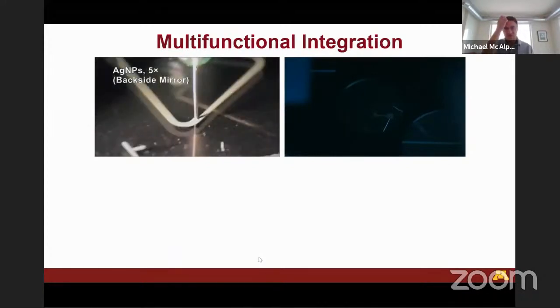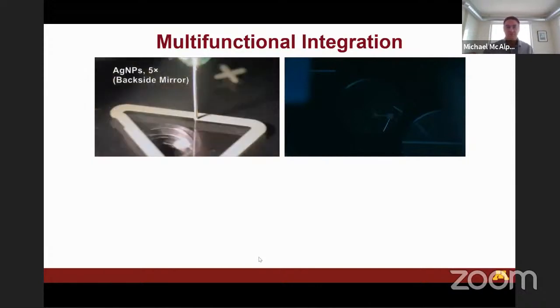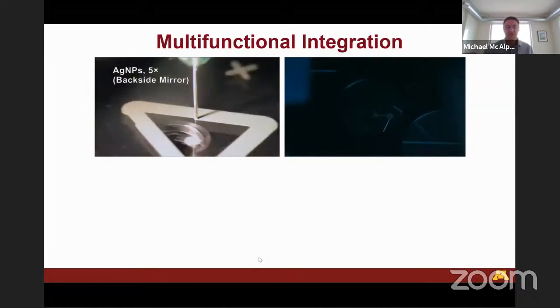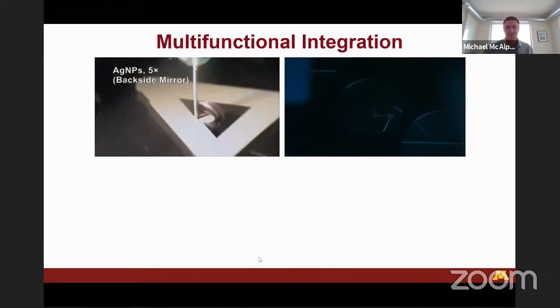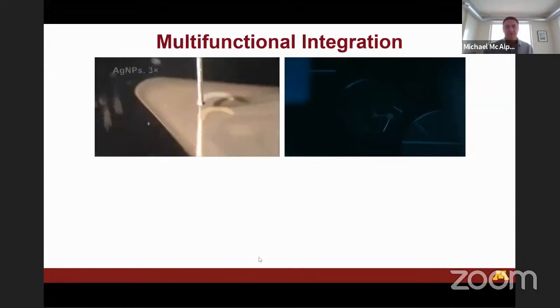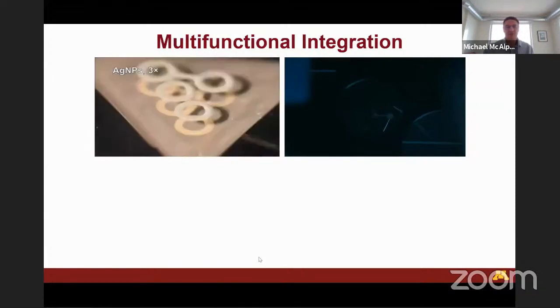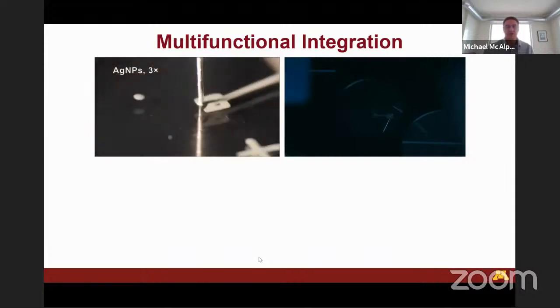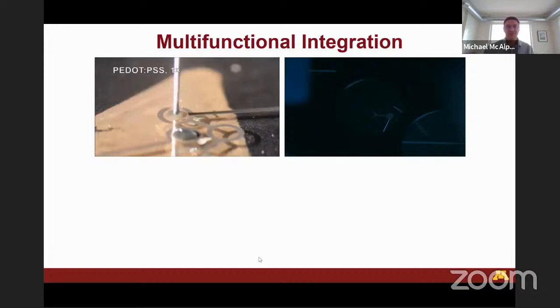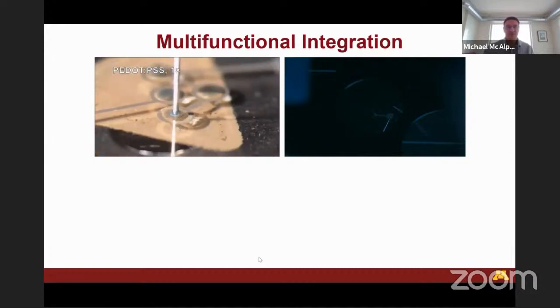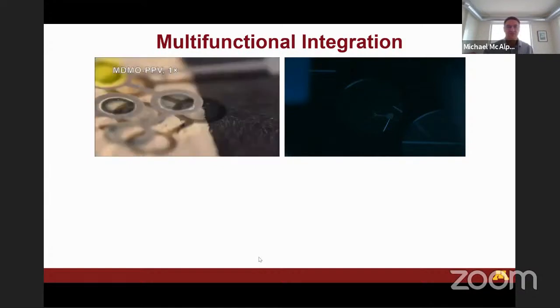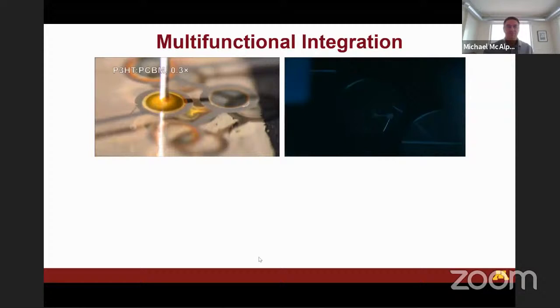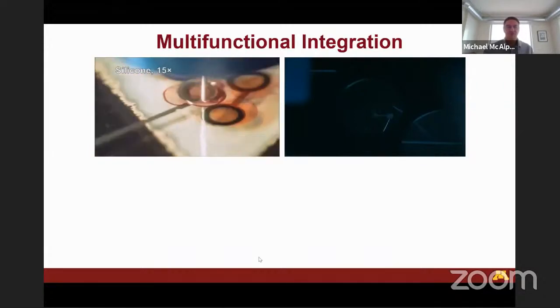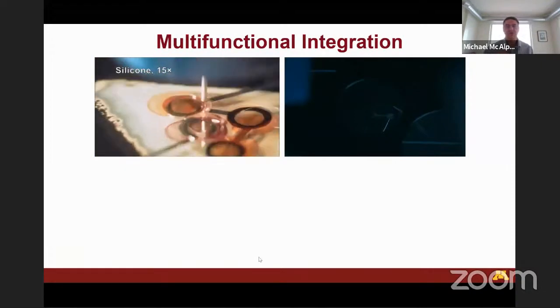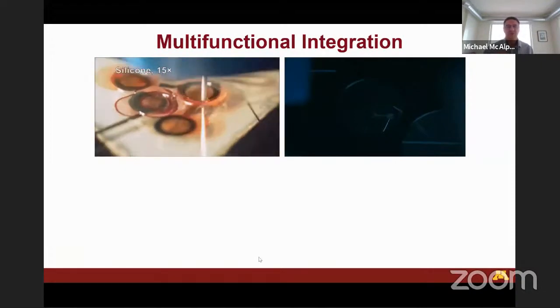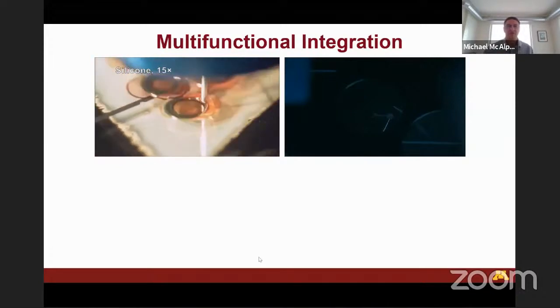So here we're actually printing a silver nanoparticle mirror on one side of a piece of glass. And then we flip the glass over, and on the other side of the glass, we print 4 devices. So the outer 3 devices are LEDs, and the inner device is a photodetector. So when the LEDs light up, the light bounces off the mirror that we printed in the first step, and then bounces into the photodetector so that we can image the light that's bounced off. So this may be a first step towards something like a wearable oximetry device. But you can see each of the layers here printed.